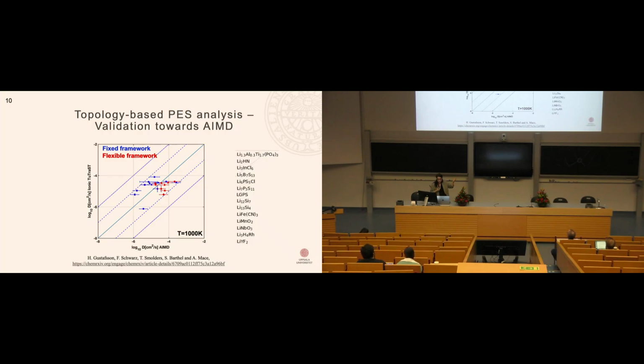So what we did to at least accomplish this is that we looked through the literature for all previously studied highly diffusive materials and ran the DFT molecular dynamics simulations at 1,000 Kelvin. You need to run these simulations at that high temperature to be able to reach a diffusive regime in ab initio molecular dynamics. So we got converged diffusion coefficients for around 15 structures, which we could validate our results against. Here, all structures that we looked at were accurately predicted within the 1 order of magnitude range that we're shooting for with this screening approach.